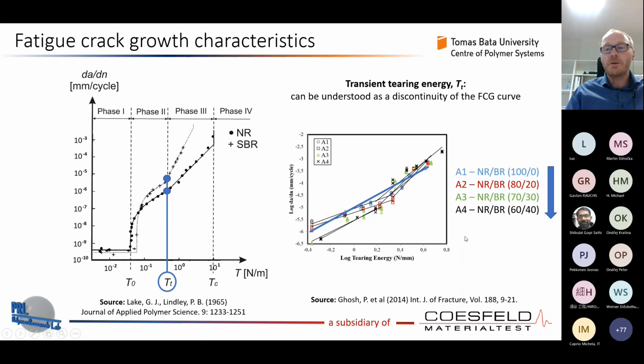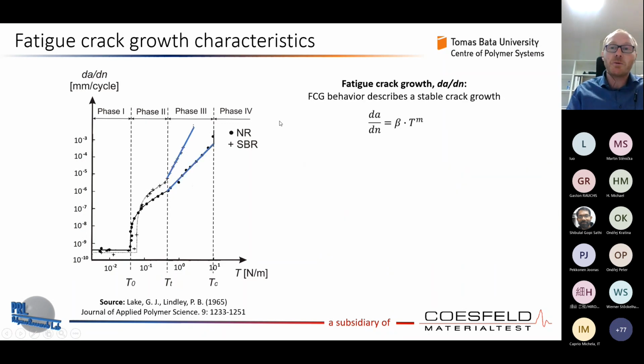So from my opinion, such a transient point can be associated with an effect like fracture mechanics in blends, some interface between two rubbers. However, in a pristine rubber there is more or less no transient point. This is important to understand and maybe to investigate.